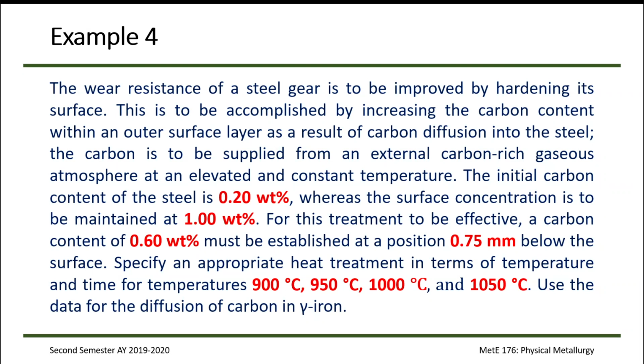So the initial content of the steel is 0.2 weight percent. So that's a hypoeutectoid steel siya, no? Our eutectoid steel is at somewhere around 0.8, no, or 0.76. So anything lower than 0.76 is hypoeutectoid. Okay? Whereas the surface concentration is to be maintained at 1 weight percent. For this treatment to be effective, a carbon content of 0.6, sorry, must be established at a position of 0.75 below the surface. So for this problem, we are to specify an appropriate heat treatment in terms of temperature and time for temperatures at 900 degrees Celsius, 950 degrees Celsius, 1000 degrees Celsius, and 1050 degrees Celsius. So let's use the data for the diffusion of carbon in gamma iron, and it should be provided here now.